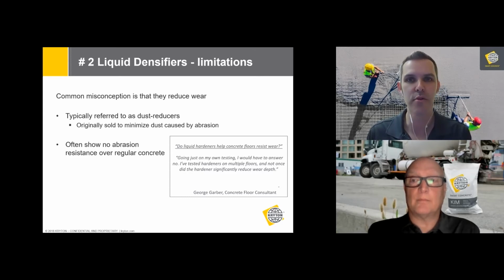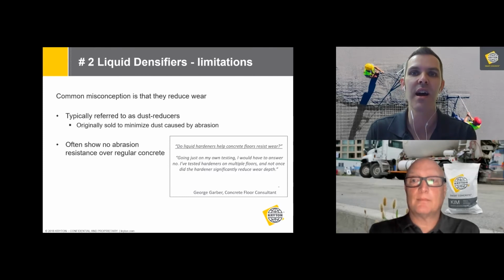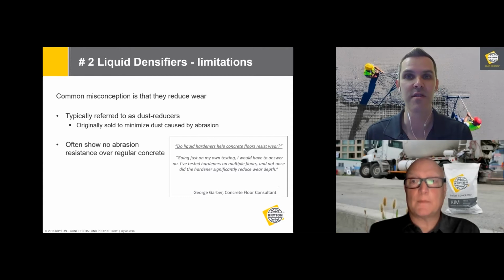Now, these products do have a role. They were originally brought to market because they were effective if you had a slab where the contractor had some difficulty getting a really good finish on it. Maybe it was windy and the surface dried out too soon and the cement didn't hydrate very efficiently. So it's weak and dusty basically from the first day you install it. These products can help as a remedial measure to try to strengthen that slab, but they're not really appropriate when you're trying to specify abrasion resistant materials for new construction.